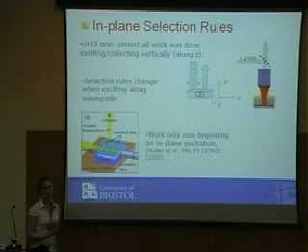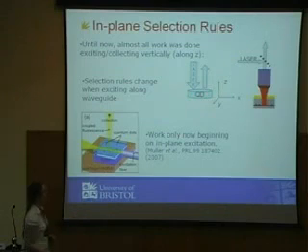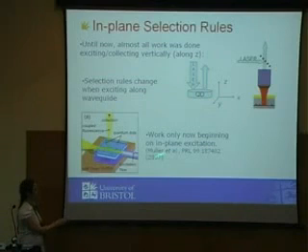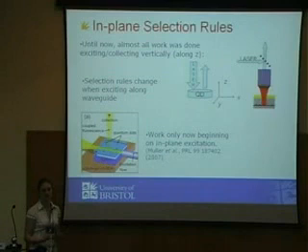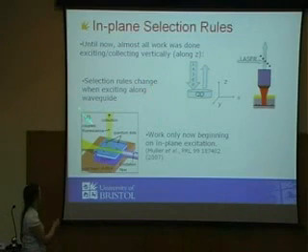And in fact, it could be that the selection rules in these quantum dots don't get preserved anymore. If you look at this quantum dot, you can see that the oscillator strength along this direction might be different than along this direction. And in fact, it's only very recently that the excitation of quantum dots in plane for single quantum dots has actually been observed. So here, Muller and co-workers actually excited the quantum dots resonantly and collected the emission this way. And they didn't yet look at the polarization selection rules. So I think there's a lot of work that has to be done, really, on investigating the selection rules before we can use quantum dots in this geometry.